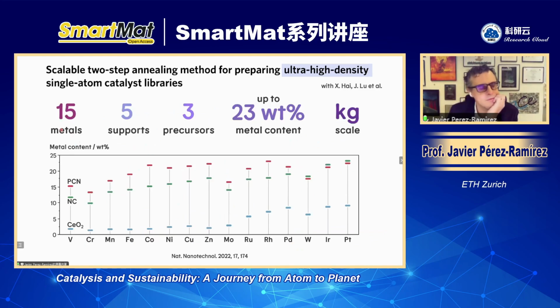Doing this, we have been able to, for 15 metals, you can see all the metals here, and 5 supports, I'm showing you here 3: ceria, nitrogen-doped carbon, and polymeric carbon nitride, prepare materials with up to 23% metal content in single atom form with single atom dispersion. And very important, this has been prepared even on kilo scale, because that's a very important aspect of our synthesis method. This is scalable. Many of the catalysts that we have prepared, you can see here for PCN, for instance, we can make 22, 23%.